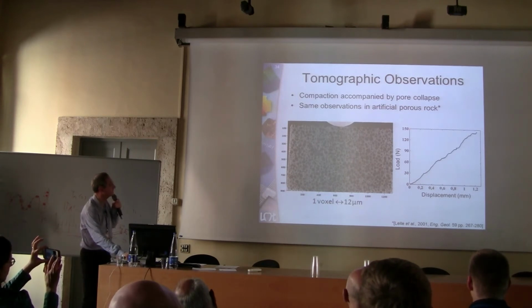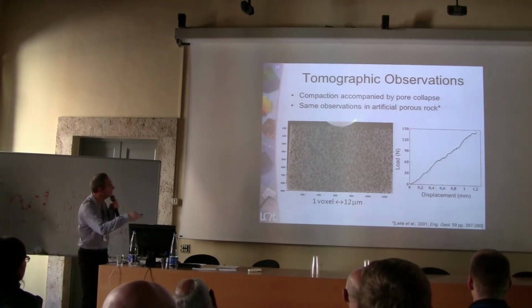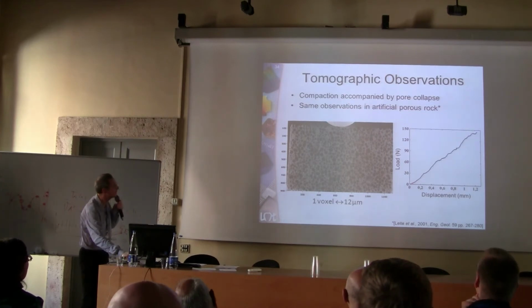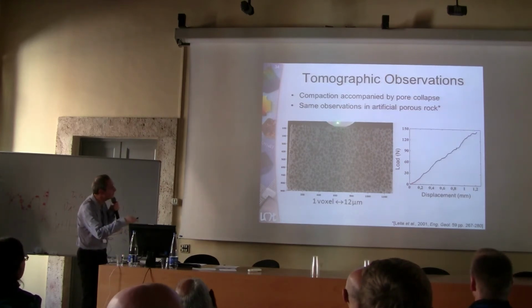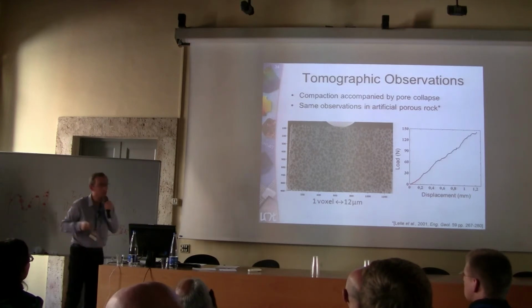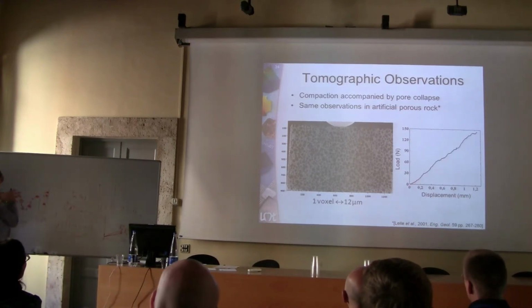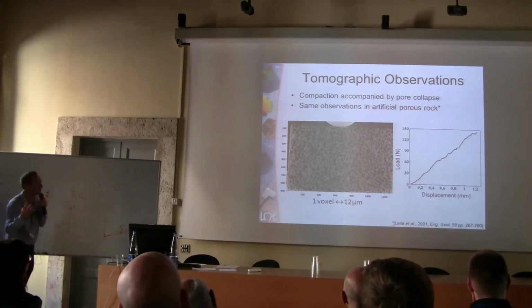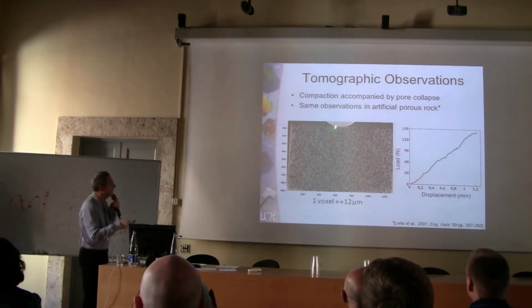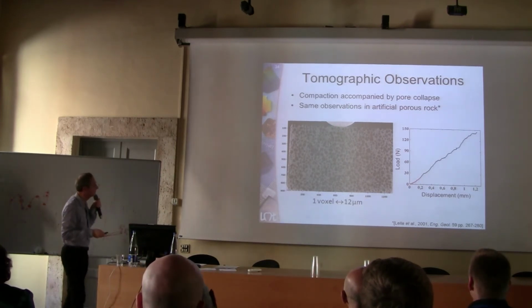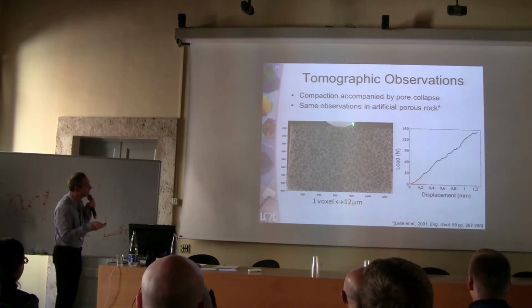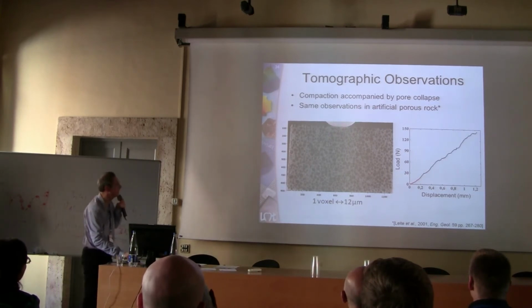What you see initially is indeed the beginning of an indentation, and very early on you actually have some pore collapse, because plaster is a brittle foam. So as you push the indenter, you will have this crushing mechanism that develops, as we will see.